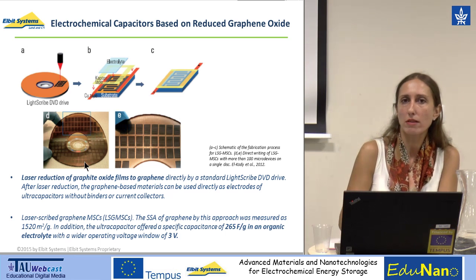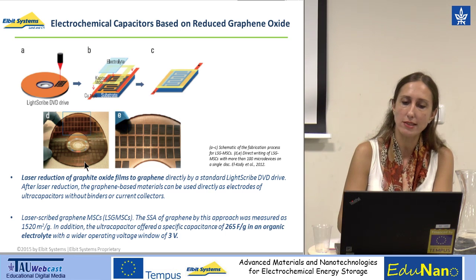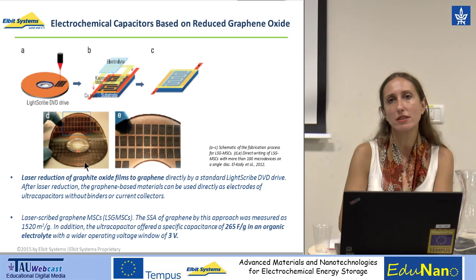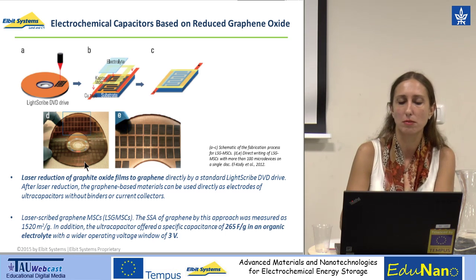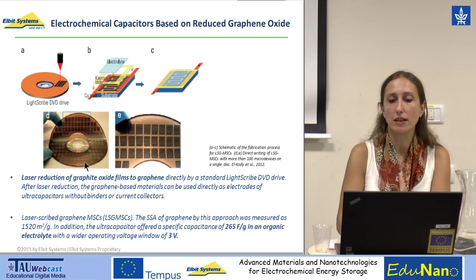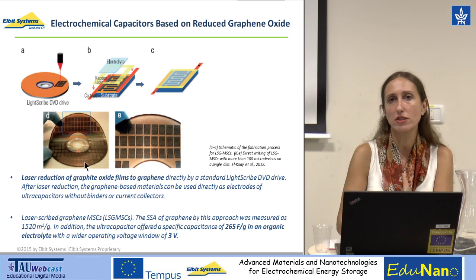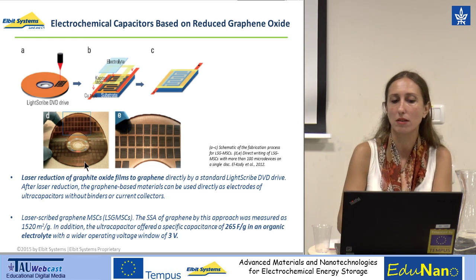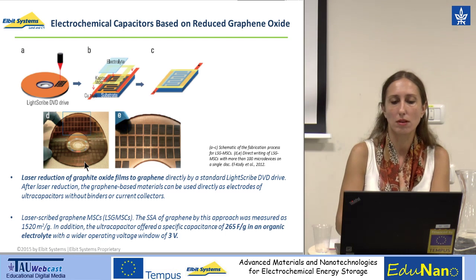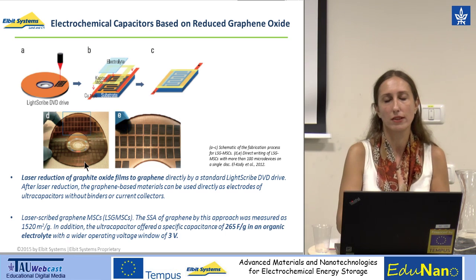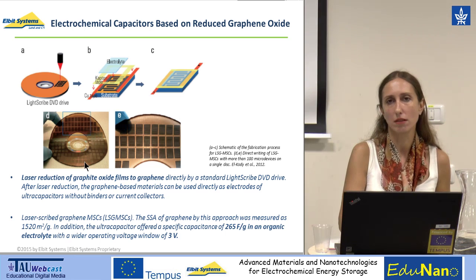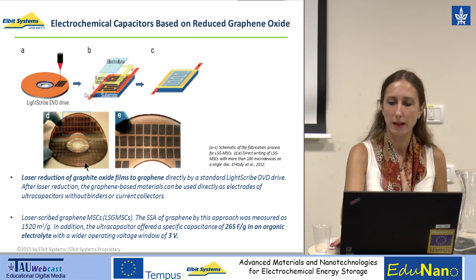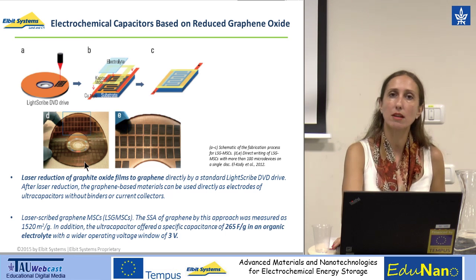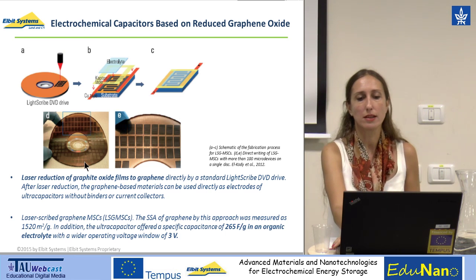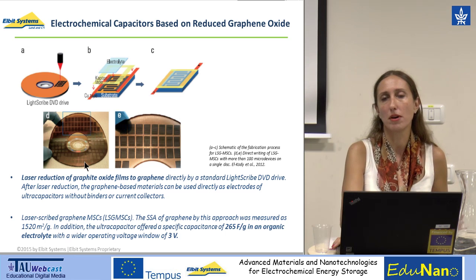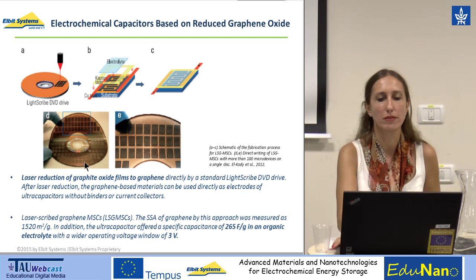So what are the properties? This looks very nice, and they also tested that. The surface area by this approach was measured as approximately 1,500 square meter per gram. A very large surface area, and in terms of the specific capacitance, the capacitor showed a capacitance of 265 farad per gram in an organic electrolyte. And of course, due to the utilization of an organic electrolyte, you have a wide operation window of maximum 3 volts. So this is a very innovative, very interesting and cost-effective method of having this kind of micro capacitors or thin layer capacitors deposited without any binder, without current collectors, directly on top of a CD.